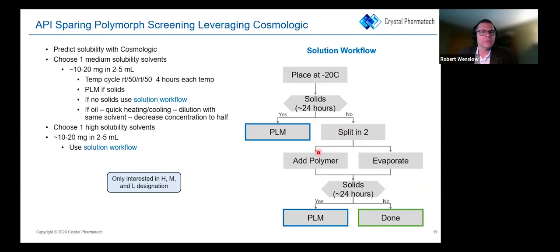Add some polymer in one of those to try to get it to crystallize, and the other one do a very slow evaporation to try to release supersaturation. It was already placed in -20 to drop solubility, or to increase the supersaturation. But now we're going to try to slow evaporate it. You don't want to rapid evaporate it because that most likely will lead to oils or amorphous material.